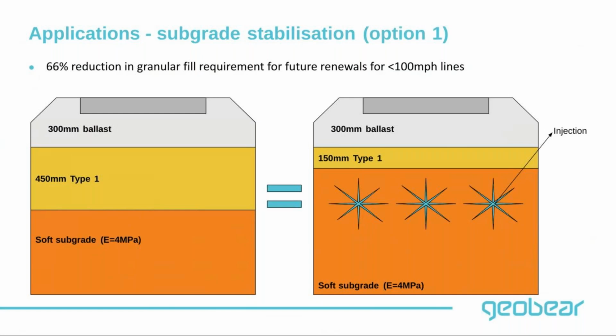For example, you've got a soft track, and that track has a soft subgrade with a modulus value of 4 MPa. Now, if you go to the Network Rail standards, your design should be 300 mm of blanket plus 450 of Type 1. However, if you do the injection in this sort of configuration into the subgrade, you could reduce your design requirement from 450 to 150 of Type 1. So it's much shallower than what you would have had initially, because you simply strengthened the ground and your subgrade has a much higher modulus than what you initially started with.